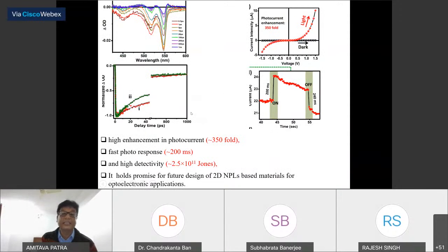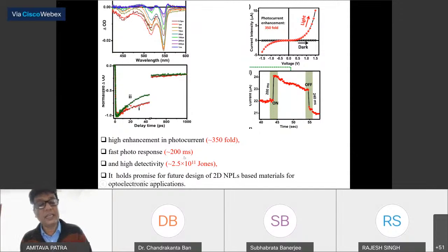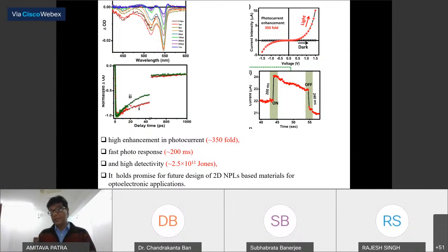And in this heterostructure system, we generate a photodetector, because silicon wafer is being used for the photodetector in the visible range. But interesting thing is that in this system, we generate a 350-fold enhancement of the photocurrent and a very high detectivity value, that is 10 to the power 11 Jones. That is very close to the silicon wafer. So this material can be used as photodetector, and photo response is 200 ms. That is very promising material. So 2D structure based material can be used for optoelectronics application. As a proof of concept, we have shown that this material can be used for photodetector.